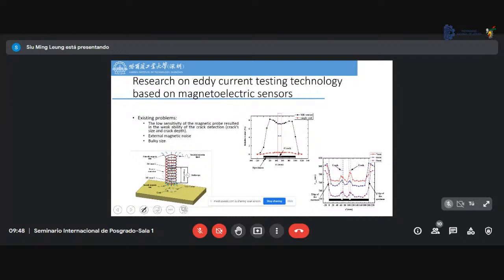testing of materials. We can imagine that there is some material with a crack on it, and we use the eddy current method. We know that when we apply a magnetic field on the material, there is some eddy current generated on the material if it is a conductive or metal material. So we use this method to detect the eddy current change caused by the crack. So this is the combination of it.